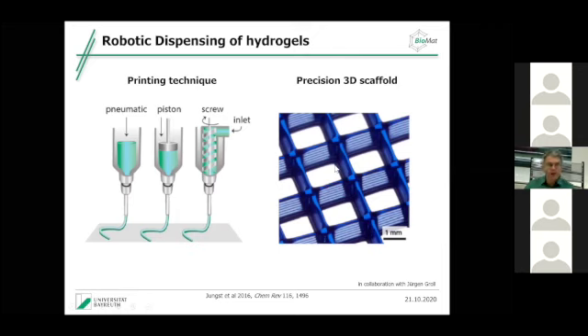If you have a good bio ink, this is what we call a bio ink that has this behavior, that it's hard without any shear force. You press it, it starts to flow. Then it's a good bio ink. And you know this behavior from toothpaste. I mean, toothpaste is not perfect because it also shows some instabilities later on, but in principle, if you have toothpaste in the tube and you open the screw, nothing happens. You have to squeeze it so that it flows, right? And that's pretty much the same principle here.